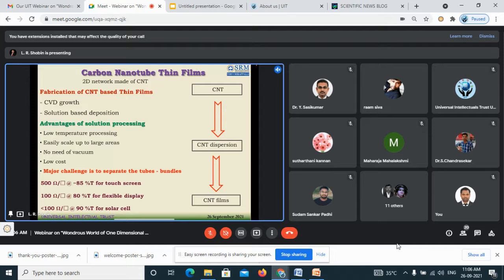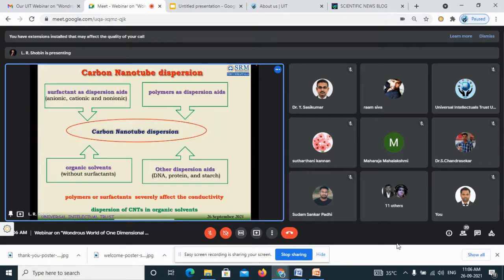So our aim is to produce 100 ohm per square resistance with 90% transparency. So what I did is I took a CNT powder, made a dispersion, and then simply sprayed the tube dispersion. Okay, we have a powder. Say, for example, you have a carbon nanotube powder or a black carbon powder. How can you realize a dispersion?